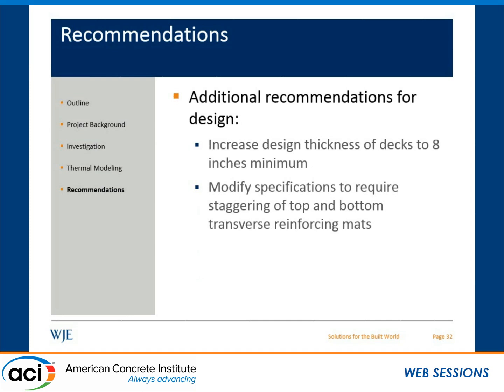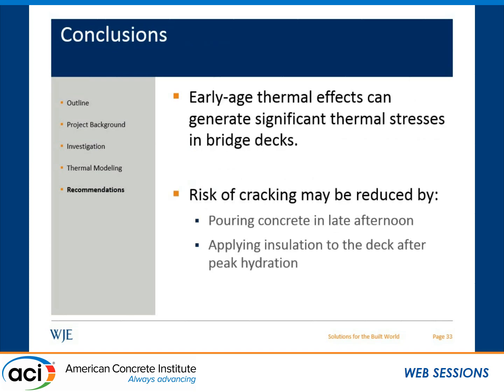But our stress analysis indicated that the thicker bridge decks helped reduce some of those stresses. And finally, we recommended that they modify the specifications to require staggering of the top and bottom transverse reinforcing mats, because as we saw in that very first photo, if they aren't staggered, then holes can develop and the concrete can go right through. So just to summarize, we found that early age thermal effects can generate significant thermal stresses